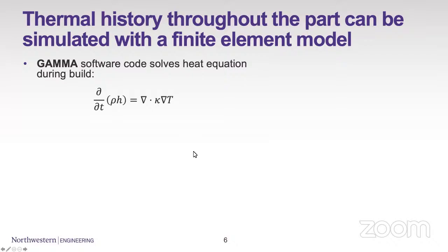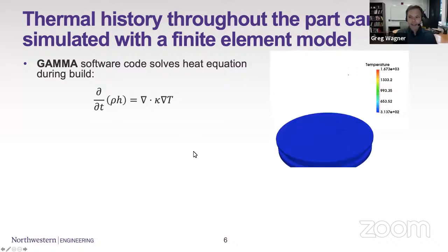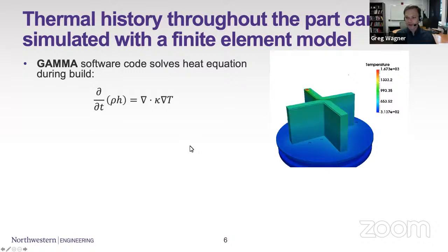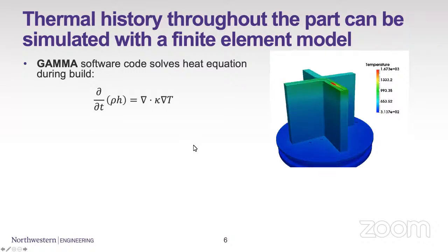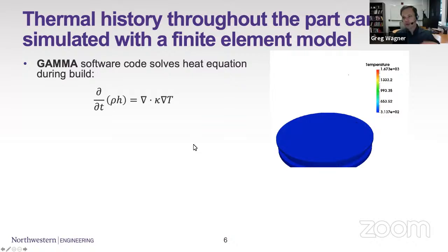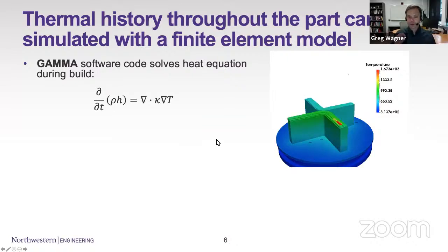On the part scale, we have developed a finite element model of the thermal history throughout a part. And this is a fairly straightforward model. It's just solving the heat equation in enthalpy form. And this allows us, I don't know how well movies are coming across on the video, sorry, but we can build a part, trace the thermal history throughout the part. Basically, what we're doing is tracking the same laser path in detail, at the laser scale. So we're capturing all of the details in the laser path, the material addition.